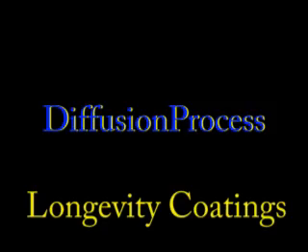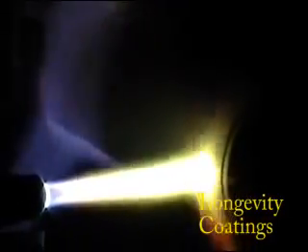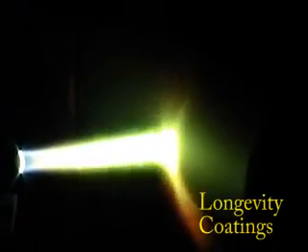The coating being applied in this video is a nickel-chromium hard-facing alloy and is being applied through a process generically known as diffusion bonding. After the coating is initially applied, it will subsequently receive post-treatment where the coating is brought up to its plastic state and densified in the process. Properly applied, diffusion-bonded coatings produce a fully dense, hard surfacing with a metallurgical bond.